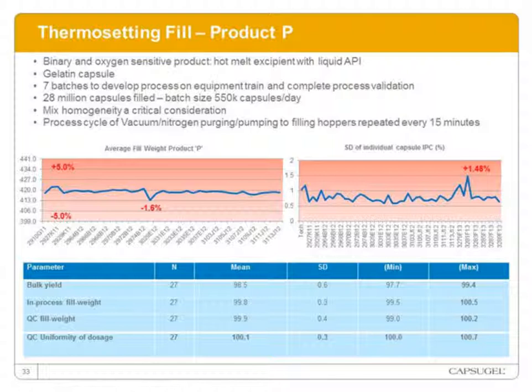So again, we've developed some very interesting automatic process cycle here, where the product needs to be vacuumed to degas after the very intensive mixing, and then prior to pumping over to the filling hoppers, the tank has to be returned to ambient pressure with nitrogen. And I'm going to show you some of the actual setup on the equipment on the next slide. On this slide here, we just see across a range again of 20 batches, we see excellent fill weight control with standard deviations less than 1% generally.